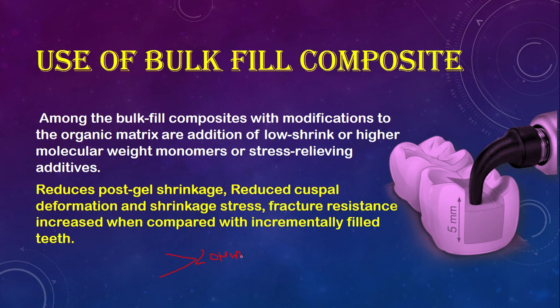More than 20 micrometer. The difference in the composition of the bulk fill materials leads to a lower total filler matrix interface, and we know that the lower the total filler matrix interface, the lower the generation of the shrinkage stress, and consequently less shrinkage development.